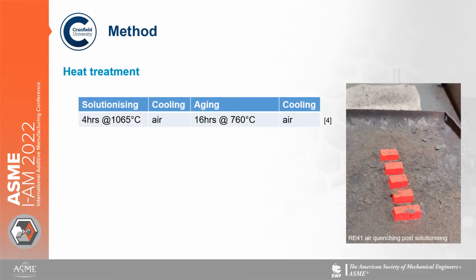So the heat treatments we used was a standard heat treatment from literature, which included solutionizing at 1065 degrees Celsius for 4 hours, followed by air quenching, and then a further aging at 760 degrees for 16 hours, again followed by air quenching. And you can see a nice picture on the right there of our metallographic samples coming out of the furnace post solutionizing.